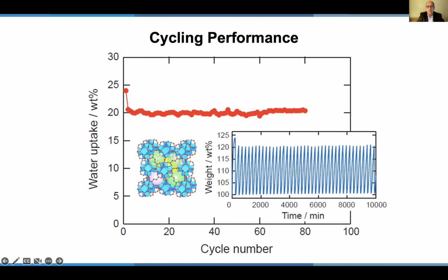Now, you notice here that after the first cycle, there is a loss of water capacity. The water capacity in this particular experiment is 25% by weight. After the first cycle, you see it goes down to around 20% by weight and then stabilizes. It turns out that this water, later I'll show a video to show what happens to this water.